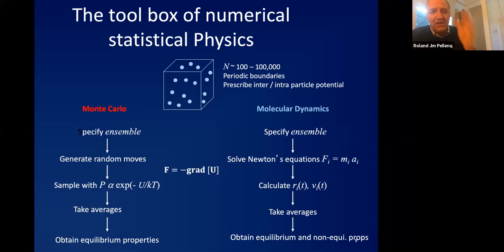With Monte Carlo, we generate those configurations in a random way, and then we average over them. So you specify the ensemble. That's the constraint in terms of, do I have a constant volume? If I have a constant volume, then I can calculate the pressure as a conjugate variable, for instance. If I have a constant pressure, then I can calculate the volume. That's an example of those conjugate variables. These are constraints that specify a statistical ensemble. But then we average the thing, either over a number of configurations for Monte Carlo or over time in molecular dynamics. So in one case, we do ensemble averaging, the other one we do time averaging.